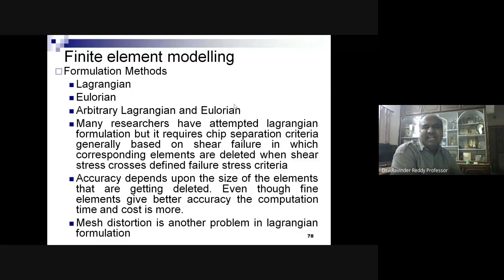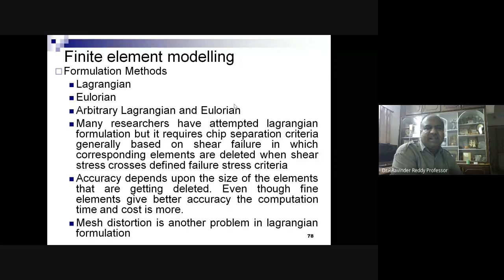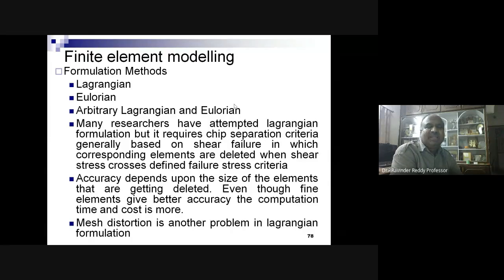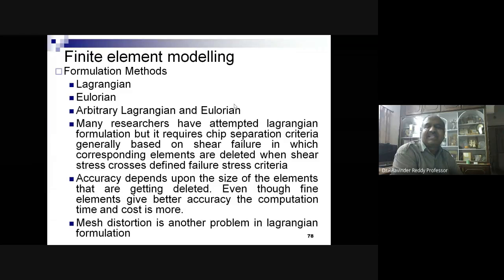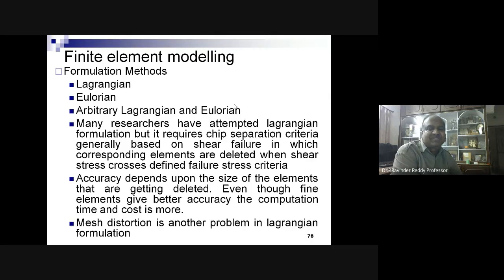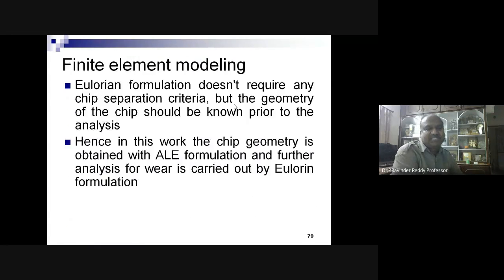For formulation, Lagrangian, Eulerian, and arbitrary Lagrangian-Eulerian, all three are possible. Many researchers have attempted Lagrangian formulation, but it requires a chip separation criterion based on shear failure, in which corresponding elements are deleted when shear stress crosses the defined failure stress criterion. Accuracy depends on the size of the elements that are getting deleted. Even though fine elements give better accuracy, the computation time and cost must also be accounted for. Mesh distortion is another problem in Lagrangian formulation.